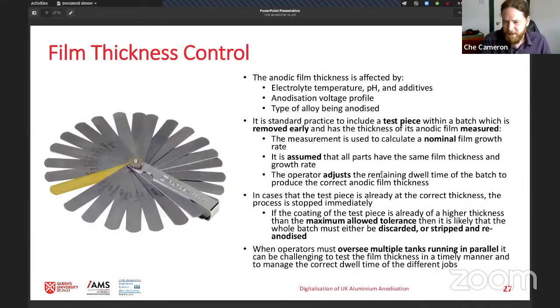So one of the critical things that we want when anodizing a part is a film of the correct thickness. And the unfortunate thing about this is that thickness is affected by the temperature of the electrolyte, the pH of the electrolyte, any additives, the voltage you're using, the type of alloy you're using. It's not a simple calculation to work out how long that should be. So the general procedure here is a test piece would be included within the batch, and that test piece is removed earlier than we'd expect the anodization process to be finished, and then we measure the thickness of the film that has formed so far. From that, you can calculate the expected growth rate, assume it's the same for all the parts, and then calculate when you should stop the process.